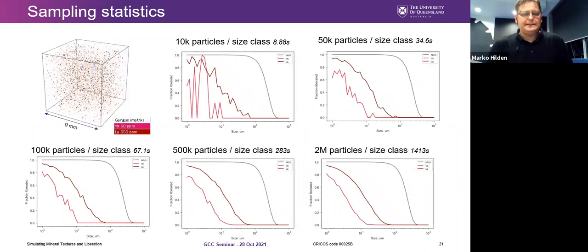Now, if I went to a much lower grade texture, and this has a very low grade, this is 50 parts per million for one of the phases, and 550 parts per million for the other phase, you can see that 10,000 particles per size class doesn't cut it. You have to go to a higher number of particles, but that increases the simulation time.